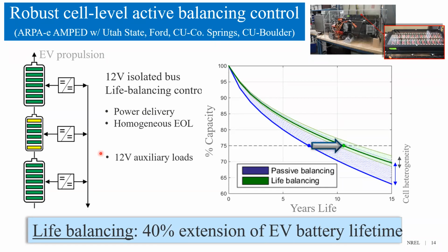Life balancing leads to reduced capacity imbalance that can be caused by factors such as pack temperature gradient and slight manufacturing variance among cells, increased lifetime, and relaxed thermal management. Range is no longer limited by the weaker cell in the pack. The proposed system architecture and life balancing were experimentally validated. For fast charging applications, it's expected that life balancing will be more beneficial.